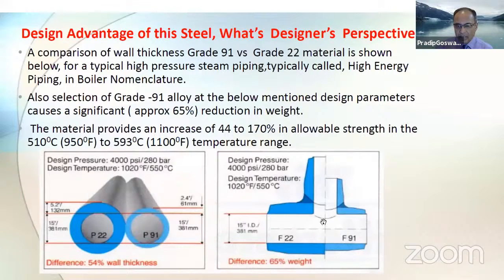And on the right, you see a typical forged component. When you talk about an F22 versus F91, there is approximately 65% savings in the weight. These are typically the design considerations under the fossil fuel plants. Typically, the pressure is as high as 4,000 psi, and the temperature is as close to 550 degrees centigrade, which is pretty high.